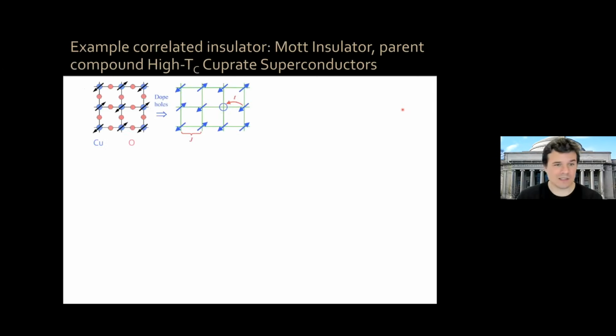Now, there are different examples of correlated insulators, okay? One of the most famous is the Mott insulator, which is the parent compound of the high-Tc cuprate superconductors. So now in the cuprate superconductors, the key element is this copper-oxygen plane, where when you have a stoichiometric compound, you have one electron per copper atom. You could have up to 2 electrons per copper atom in that orbital, spin up and spin down, but you have 1 electron per copper atom. You are half occupying that system with electrons. And it turns out that due to the strong Coulomb interactions between these electrons, the electrons get stuck in their locations and they cannot conduct electricity.